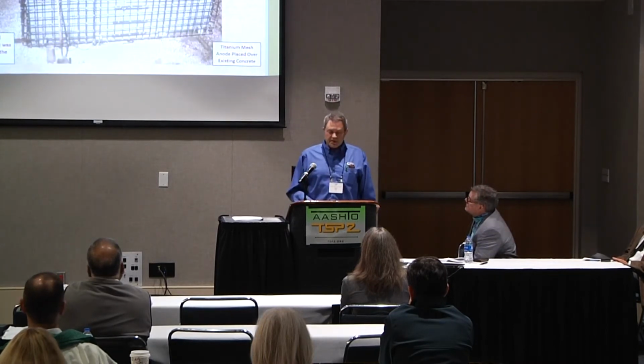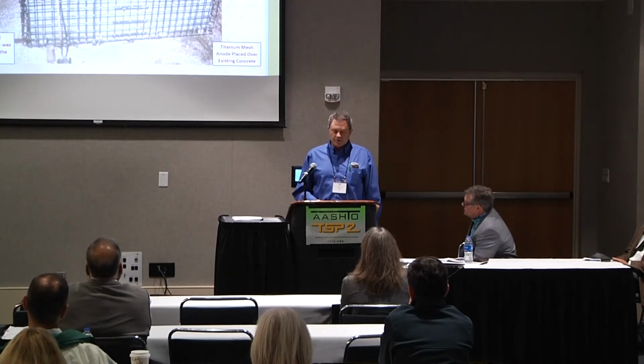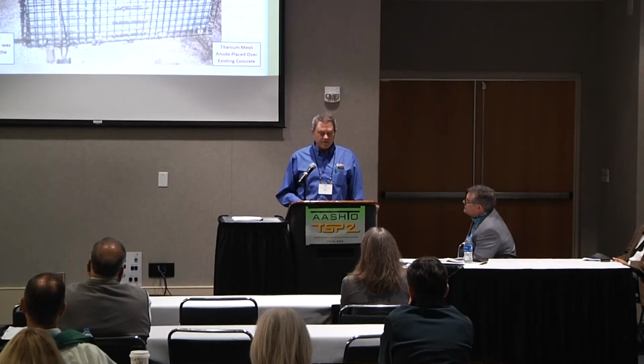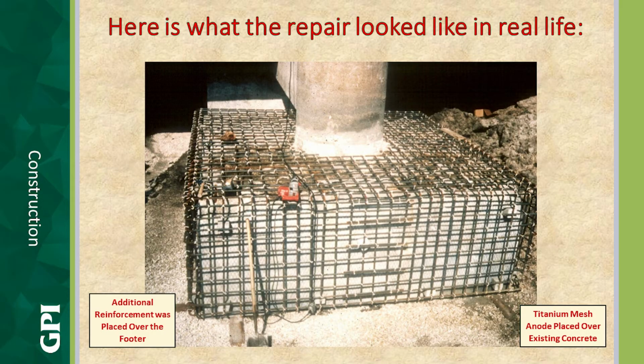So the Crescent Beach pier caps received an impressed current cathodic protection system. The existing concrete was repaired. A titanium mesh anode was installed along with additional reinforcement to restore the structural integrity. The pier footing still needs to be formed, but is almost ready for placement of the new concrete. And in the picture, it's a little bit blurry, but you can see behind the reinforcement that the titanium mesh has already been installed.